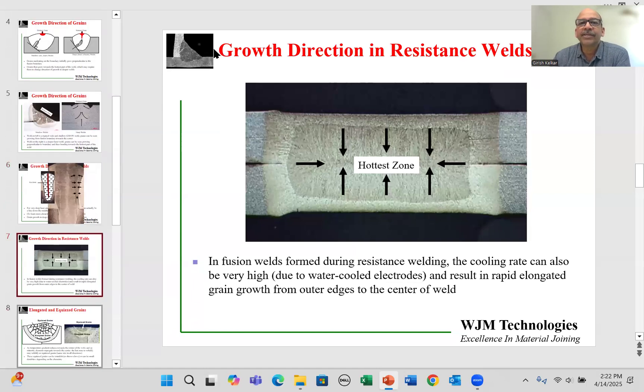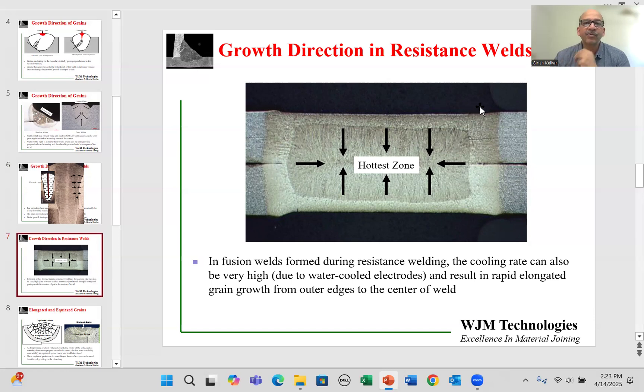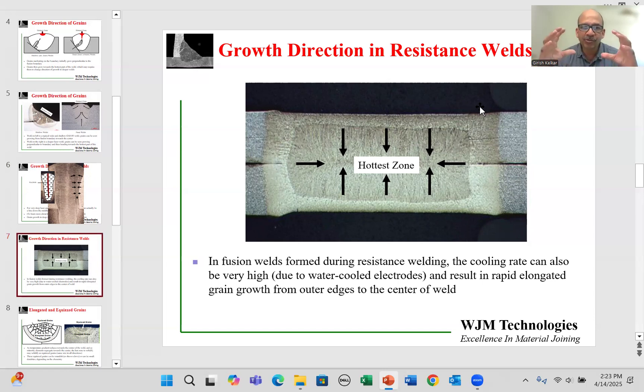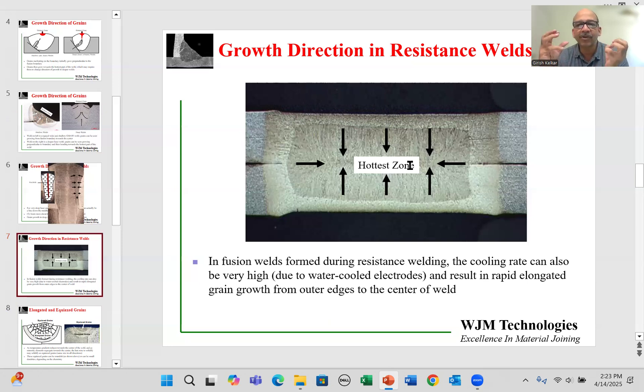On the next screen, we can see growth direction in resistance welds. The same thing happens in resistance welding — you have the fusion zone, but the only difference is the fusion zone is contained on the inside and is surrounded by solid metal, with the electrodes also taking a lot of the heat out. So when you turn the current off in resistance welding, the fusion zone starts to solidify towards the hot zone, which in this case is a line along the center of the weld. Here we can see external grains growing from the outside towards the center line — rapid, long, elongated grains from the outside edge to the inside edge.